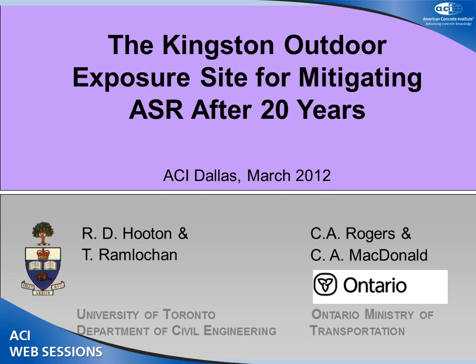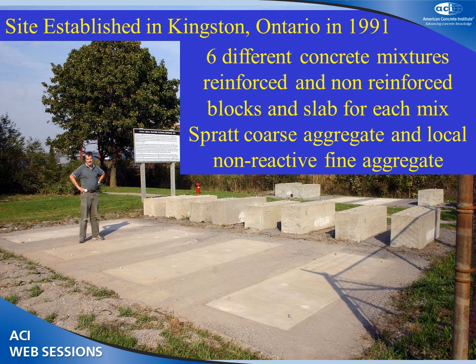We actually looked at things like chloride diffusion, freeze-thaw resistance, and de-icer scaling, because the ministry was looking for solutions for ASR, but they were also concerned that if they used high-volume slag replacements, which is the most common SCM in Ontario, they would perhaps run into other issues, and they wanted to know what those were. It actually improved chloride resistance, and the scaling resistance wasn't much affected. There's Chris there, standing on his site.